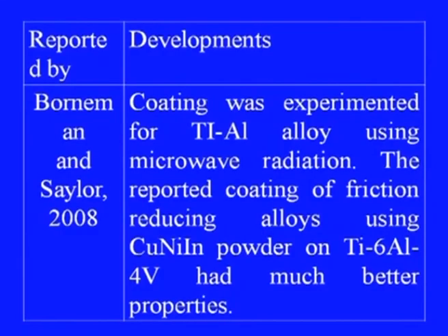Another group, Borneman and Saylor, successfully developed coating for titanium and aluminum alloy using microwave radiation. They reported the coating of friction reducing alloys using copper nickel indium powder on titanium 6 aluminum 4 vanadium alloy, and they found better properties of microwave induced coatings.